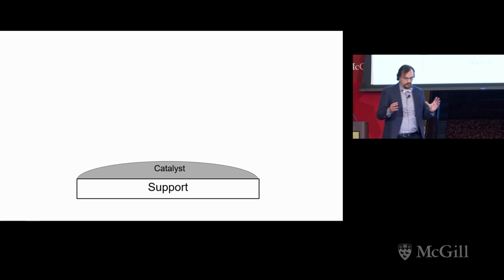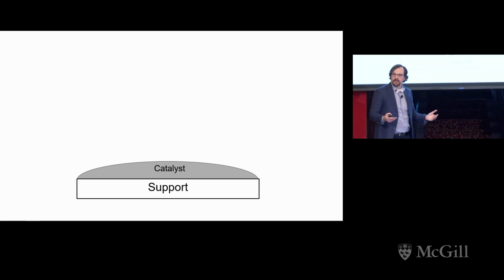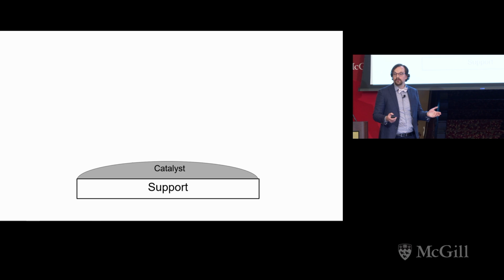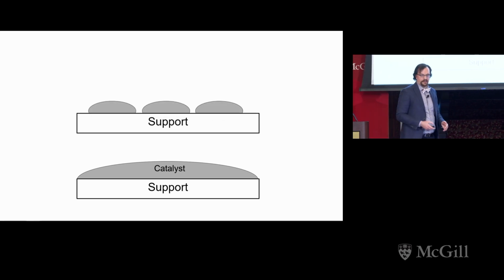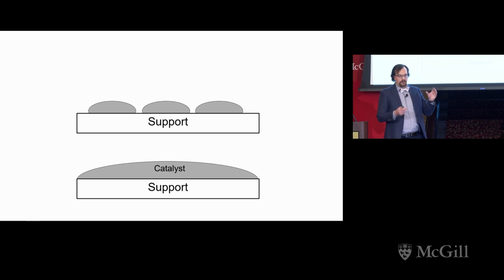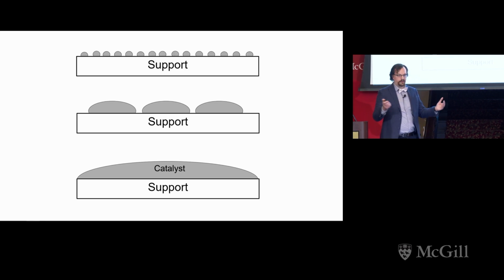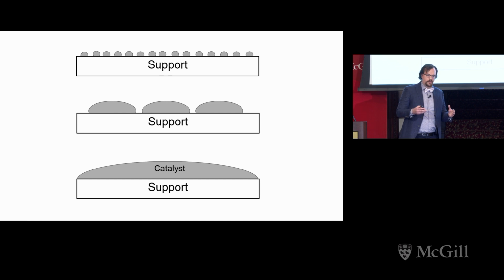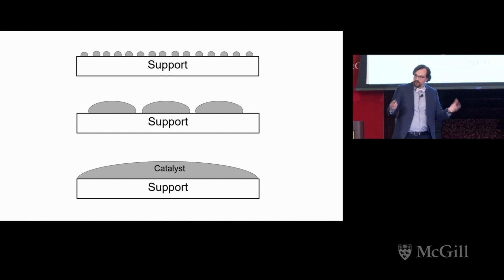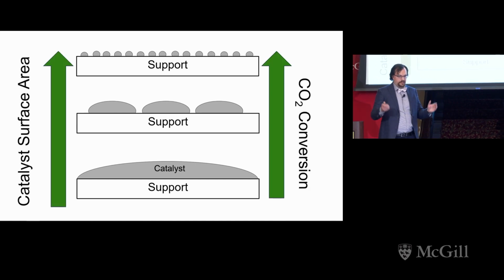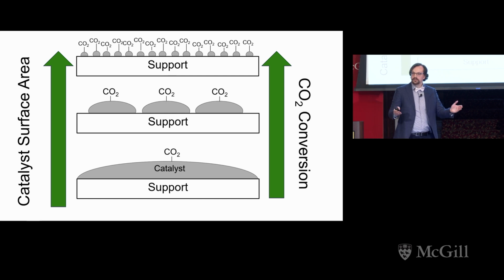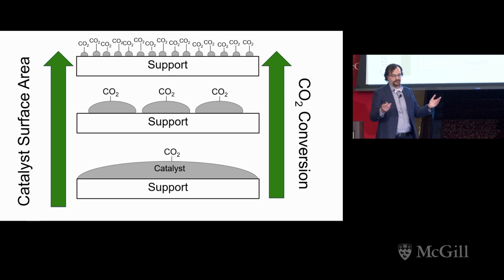Now, what we want to do is increase the conversion of our catalyst. One way we do that is by adding a support. The reason is we want to increase the surface area of the catalyst. The support can help anchor the catalyst into smaller particles. The smaller the particles, the higher the conversion. The way to see this is you can put more CO2 active sites on the surface.